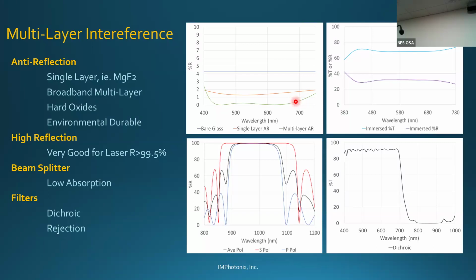produced in the industry, from single-layer mag fluoride, which this gentleman had explained was the first, to anti-reflection coatings that would involve multi-layers, so that you would get lower reflectance. That's where the red dot is. That there is uncoated glass. Single layer mag fluoride would be this yellow, which gives you 1.5% at 550.